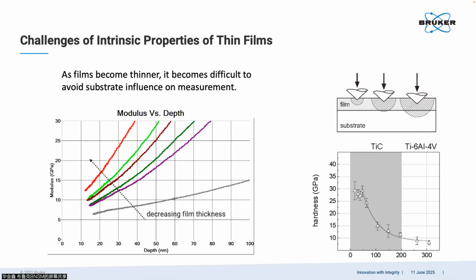Another interesting thing is that this changing behavior is highly sensitive to your film thickness. You can see this very typical behavior. If you have a thicker film, you will find that the change, no matter modulus or hardness, with contact depth is not so fast. However, if your film is very thin, the change is very dramatic. So it is also relative to the film thickness.